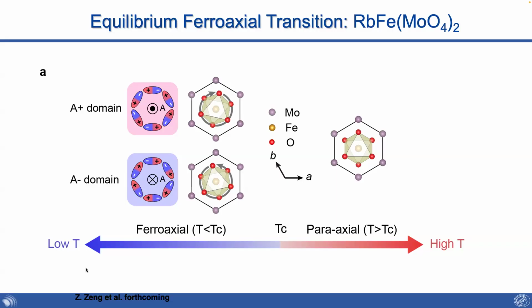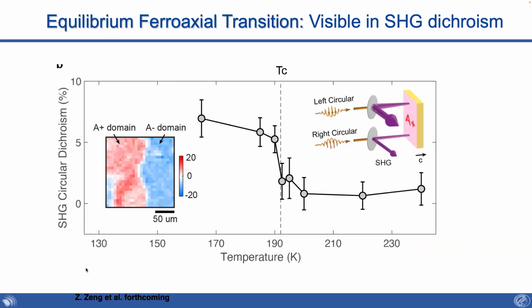It turns out that if you measure second harmonic generation with circularly polarized light, there is a dichroic signal. Imagine you have all the ferroelectric dipoles that wind like so, or all the ferroelectric dipoles that wind like so. The circularly polarized second harmonic would be different for right circular or left circular. And this is actually true. These are long measurements. But if you measure left circular minus right circular, and the ferroaxial transition is known by X-ray scattering to be around 190 Kelvin, you can now look at these A plus domains and A minus domains.